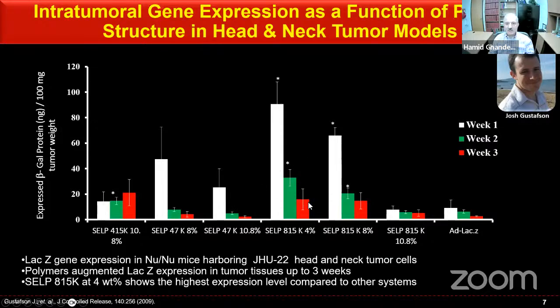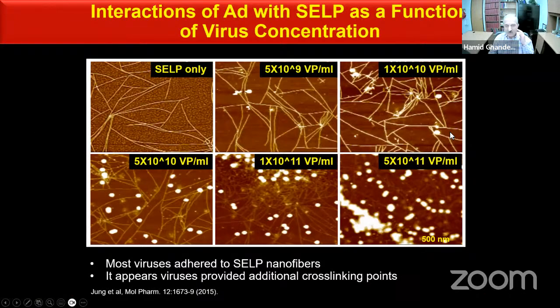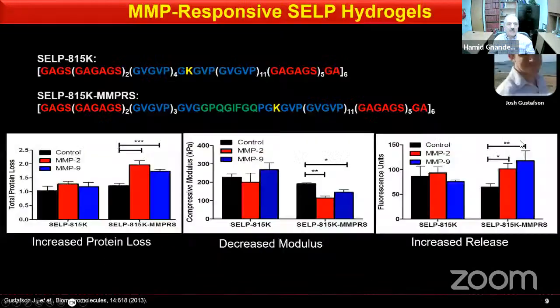But the take-home message is that by controlling the structure of the polymer, we were able to control how much of these genetic materials are released and lead to gene expression. If you were to use the same polymeric materials, but at lower concentrations that they don't form gels, and you mix them with adenoviruses, using atomic force microscopy, you can see that a lot of these viruses are really interacting with the polymers. And we think that this is in part the reason that these viruses are more stable over a period of time. And in part, that's the reason that they give more transfection efficiency. But the main reason actually is the fact that we can control the release of these materials, the viruses.